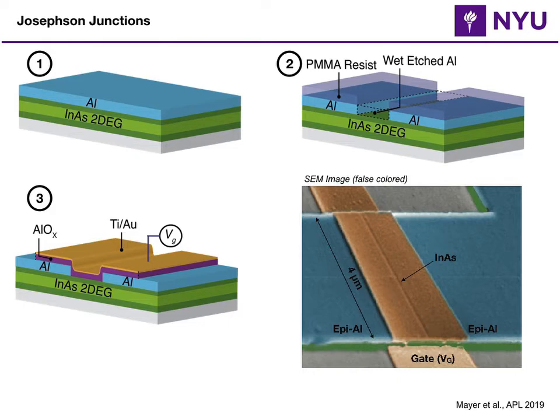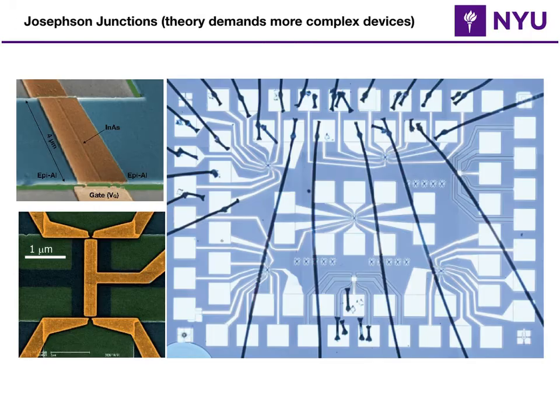The SEM image, false colored, is shown on the lower right. And you can see that trench in the middle that the arrow says indium arsenide. The junctions are relatively long, so they are 4 micron in width and 100 nanometer separation between the aluminum contacts. So we make a variety of these Josephson junctions. Sometimes there is one top gate, sometimes there are QPCs at the end. Sometimes we make them with many gates that I will talk more about in this talk.